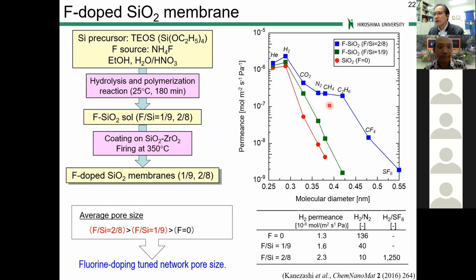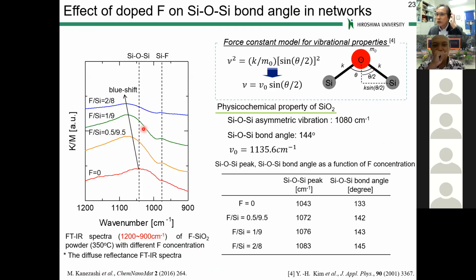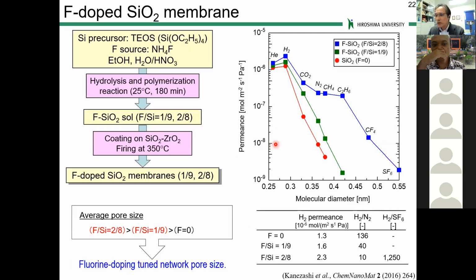Here we have the permeance against the molecular diameters. This is no fluorine, pure TEOS, fluorine 10%, and 20% here. Again, the permeance of hydrogen increased by adding fluorine, from 1.3 to 2.3. Also, nitrogen selectivity decreased. Still, we can keep the high selectivity of hydrogen over SF6, more than 1,000. We believe that by fluorine doping, the network is expanded.